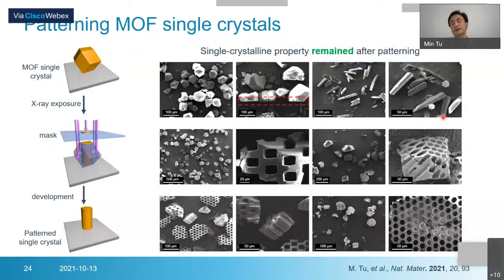And not only by patterning these MOF thin films, because of the high energy of X-ray, it has a very high penetration depth. So it can also do the patterning for thick films. And here for one demonstration, we can do the patterning of single crystals. We have MOF single crystals on the surface, then we cover them with the mask. After development, we can shape the single crystal. And here are the pristine single crystals. And here we can see a kind of knife cut on the crystal.